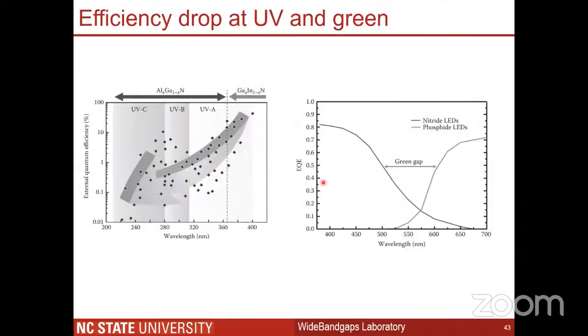By efficiently, I mean that if you look at 400 nanometers, then the efficiency is about 80%. But then if you go down to larger wavelengths, then you see that the efficiency quickly drops. So this is for nitride-based LEDs. And then the phosphide-based LEDs can enable much better efficiencies at such high wavelengths. But there is a gap which is called the green gap, because for wavelengths corresponding to green, we haven't been able to generate light emitting diodes that are efficient enough. So this is called a green gap, and many groups are working towards enabling this technology, but very few have seen success so far. So this remains an active area of research.